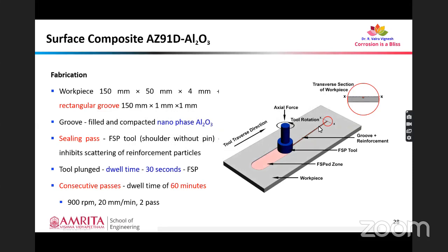So we have used friction stir processing, a solid state processing technique, to fabricate a surface composite of AZ91D and nano phase alumina. In this process, what we have done is we have taken the workpiece, then we have made a groove of dimension 150 mm by 1 mm by 1 mm, and we have filled this groove with nano phase alumina particles. Then we have done a sealing pass. The sealing pass is done with an FSP tool without pin, okay, and that ensures that the nano phase particles or the reinforcements do not come out during the normal friction stir processing.